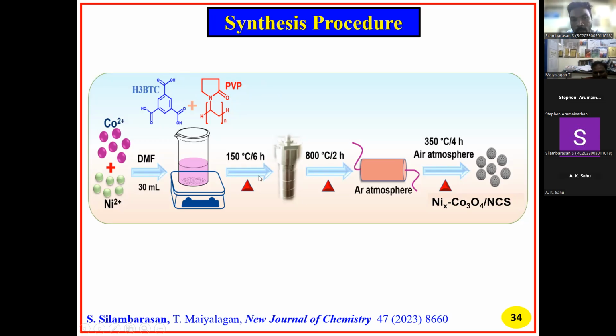After that, it was heated in a 50 ml autoclave at 150 degrees for 6 hours. Then finally, the prepared material was heated at 800 degrees for 2 hours in argon atmosphere. After that, the prepared material was calcined at 350 degrees for 4 hours. Finally, we got nickel doped cobalt oxide with nitrogen doped carbon sphere.